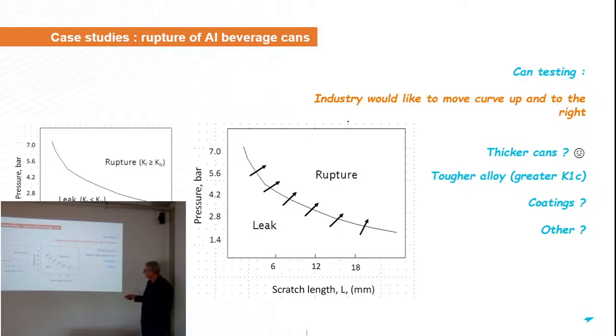Of course, what we want to do is to move this curve here to the right and up. So, what can we do to move this curve up and right? We discussed before the problem of increasing or decreasing the thickness of the can. Make the can with a material with higher toughness, a tougher alloy. Put some coating or solution. So this is a very interesting, very simple study to address the problem of material or design of the part to avoid or limit as much as possible the fracture of the can.